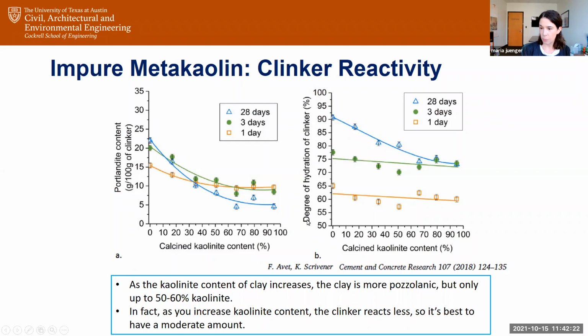So really what you want is a calcined clay that's about 50 to 60% amorphous or 50 to 60% kaolinite, because you can get the optimal reactivity of your Portland cement and yet use a cheaper calcined clay that's just as good for your properties. So there's a lot of really interesting material optimization that's happening here.